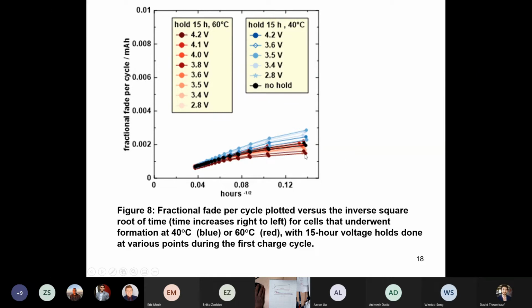And what you learn is, it's hard for me, being colorblind, to know which symbol is which, but I can tell that these are all sort of greenish or brownish, or maybe red, whereas these ones are more like blue and purple. That's the limit of my ability to distinguish them. And I can tell that all the cells that start at 60 degrees C start with a lower fractional fade per cycle. Why is that? Because during that 60-degree time, they developed a thick SEI. Okay, and the ones that started at 40, whatever happened to them, they developed a thinner SEI at 40.